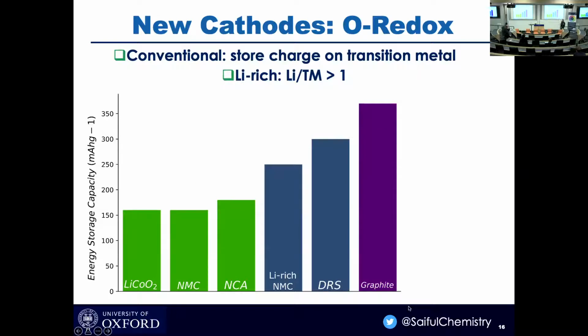The conventional cathode material stores energy by using the transition metal ion, for example, the cobalt or the manganese or the nickel. There are these lithium-rich materials where the lithium to transition metal ratio is greater than one. And that allows a greater amount of lithium into the system, but also a higher energy density. So the greens were the old cathodes I showed you, the conventional ones, and the blues in the center are these lithium-rich materials. And graphite again in purple.